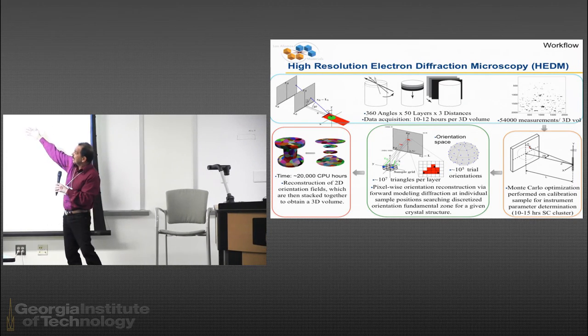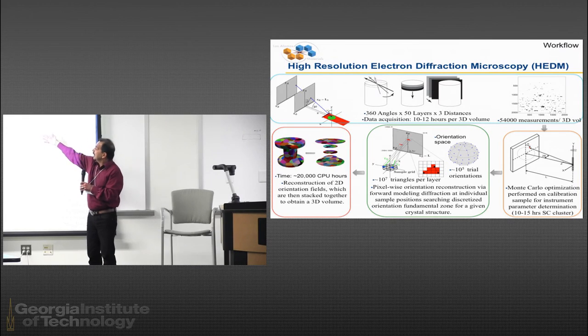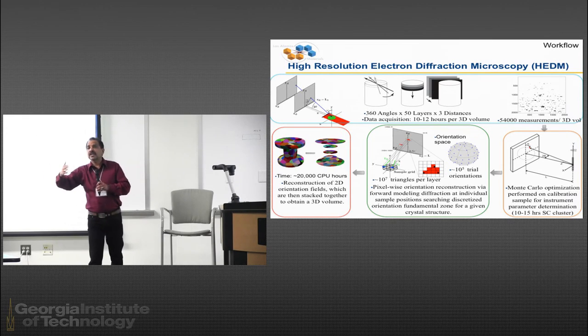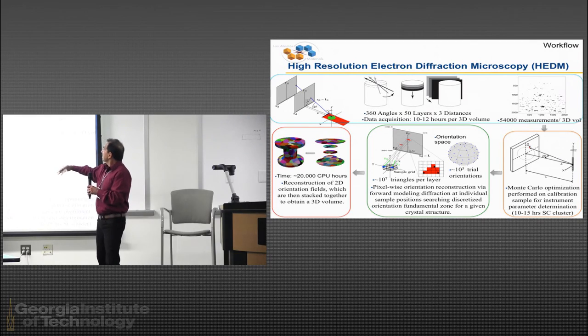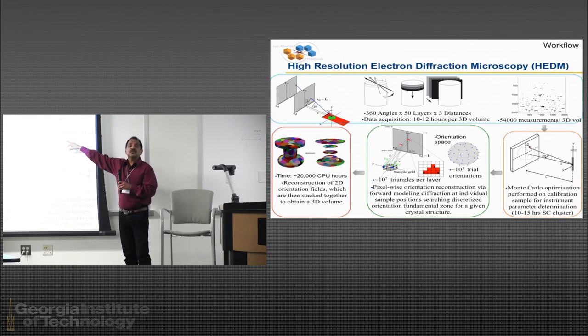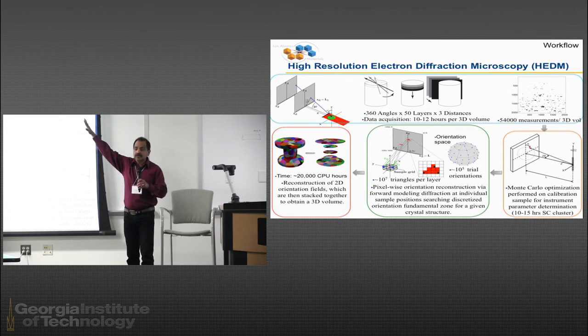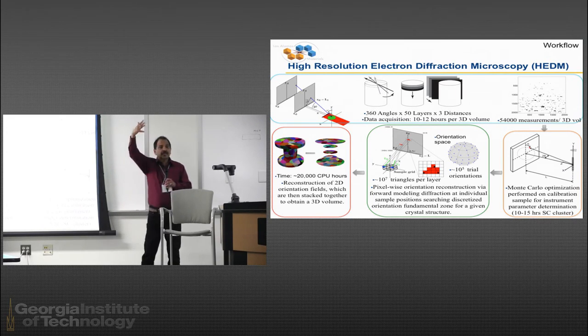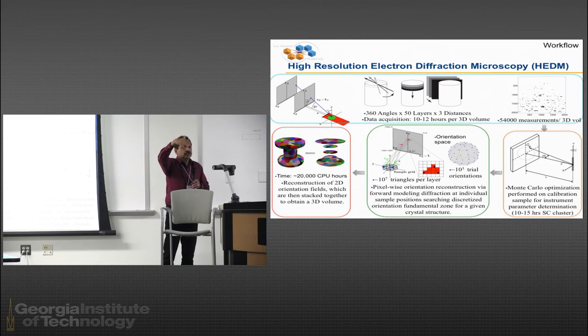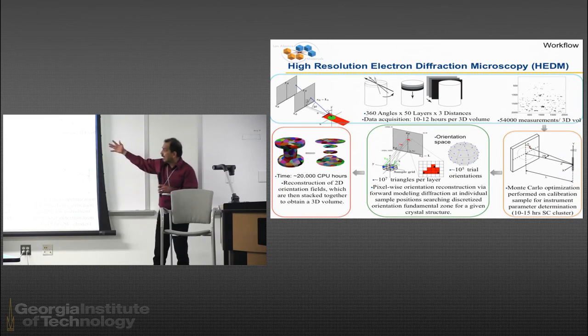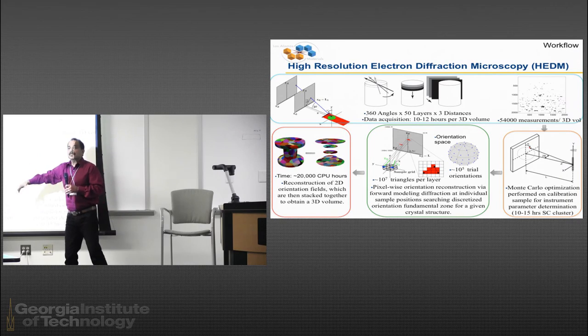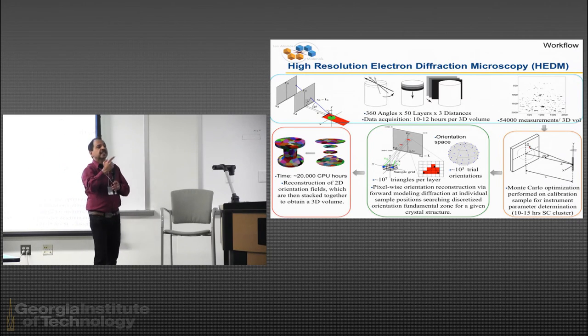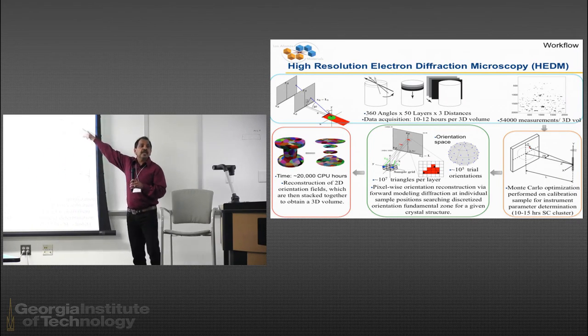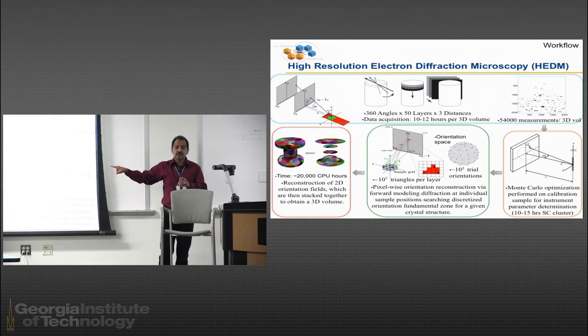You've got 360 angles, this is only 50 layers, you've got three distances, far field, near field, somewhere in between. 54,000 measurements, okay, of these diffraction patterns. So that's your data set. And then, of course, you have to calibrate the model. You've got to do some forward modeling here. You've got to calibrate the model, and then you've got to be able to find the crystal orientations that correspond to the diffraction pattern that you have. So this is a very time-consuming problem.